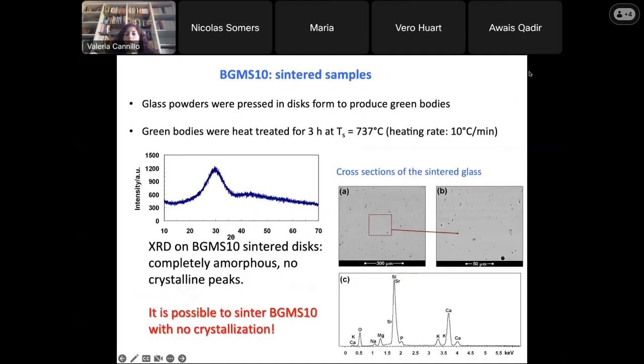So to verify that it was possible to produce sintered products, glass powders were pressed into discs to form green bodies and then were heat treated at the sintering temperature determined by heating microscopy. And here you see the XRD analysis on the sintered disc. As you can see, you have only the amorphous halo, so the product is completely amorphous with no crystalline peaks. On the right, you also have the SEM images on a cross-section of a sintered glass, so you can see that the sample is fully sintered, apart from some very small residual porosity. And so this demonstrates that it's possible to sinter the first glass, BGMS10, with no crystallization at all.